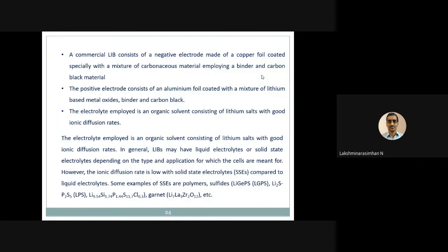And then you see a commercial LIB, lithium ion battery, consists of a negative electrode made of a copper foil. How it is being made: it is coated specially with a mixture of carbonaceous material employing a binder and a carbon black material. That's how the negative electrode is being made. They take a copper foil and coat it with a special mixture of carbonaceous materials and the binder. Similarly, the positive electrode will also be done like this. Instead of copper, they take an aluminium foil and coat it over with a mixture of lithium based metal oxides, binder and carbon black.